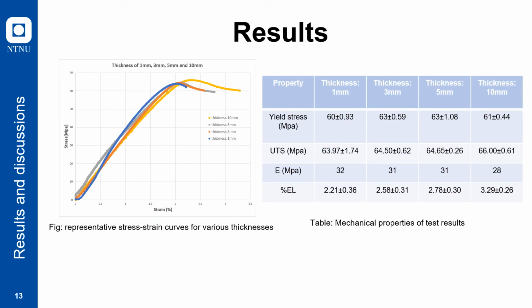So this is the result for all 4 thicknesses, as you can see from this stress and strain plot and the data we have reported in this table. As thickness increases, the ultimate tensile strength also has a tendency to increase, even though there is not much difference between the 3 mm one and the 5 mm one. And also the elongation at failure increases when the thickness increases.